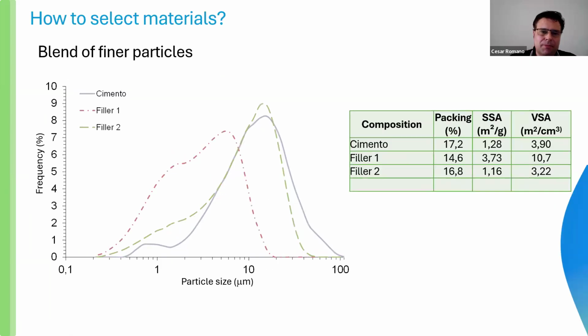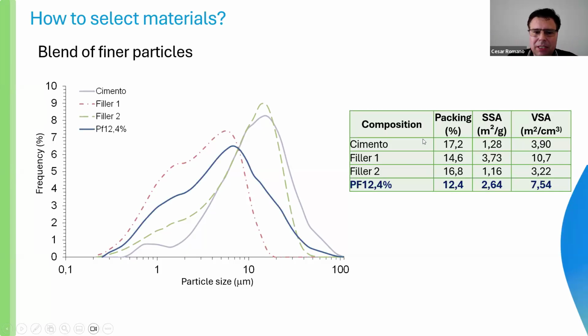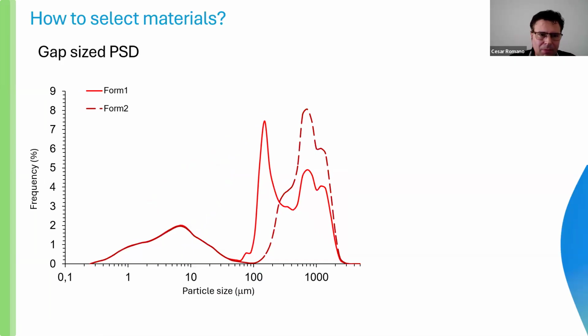for the development. We have here, for example, cement and two limestone fillers. And we have, for example, this packing of each one isolated. But when we started the combination between them, we can produce a finer particle composition with low volume of voids. And it was possible to reduce 7% in the cement consumption using this strategy here.